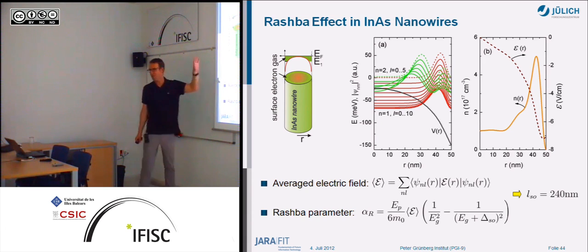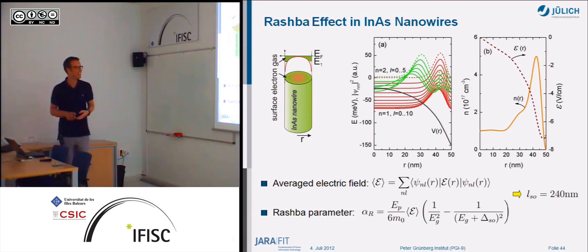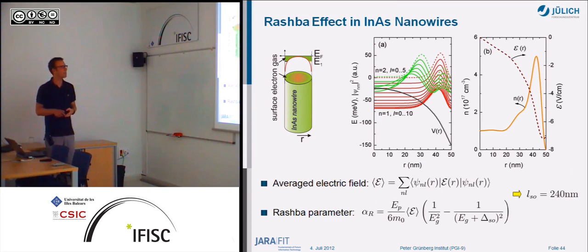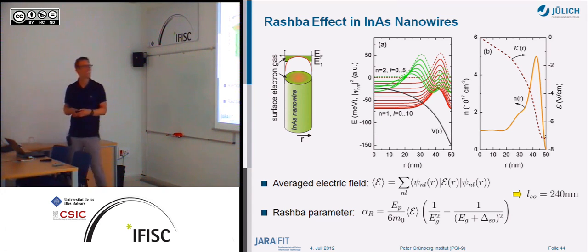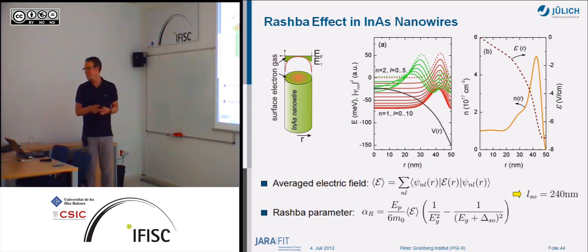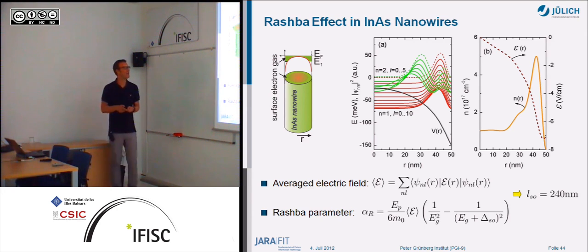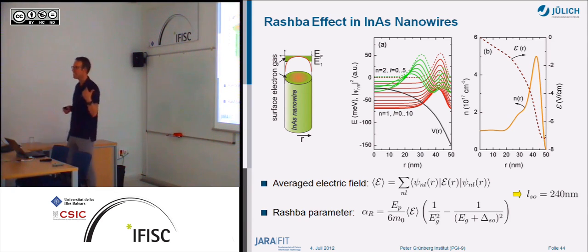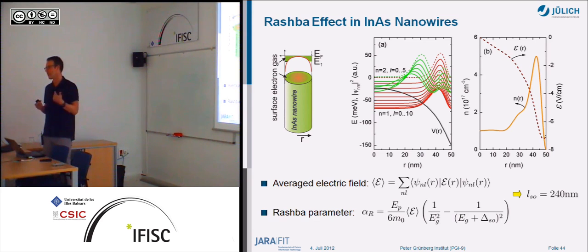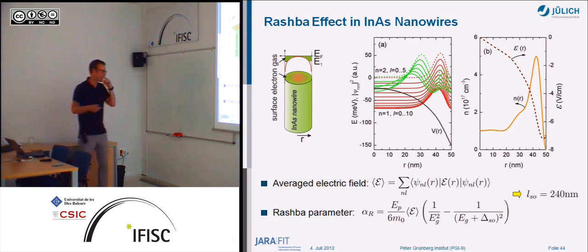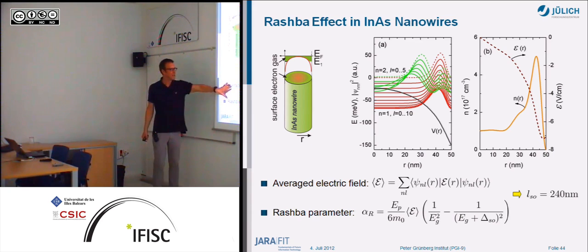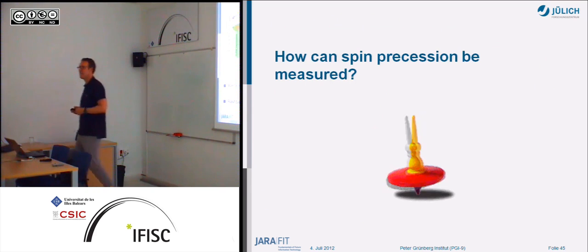To be honest, I don't feel that well about this assessment of the spin-orbit coupling lengths because, as some experts here know, you have to look at the interface as well, how the electron wave is penetrating into that barrier, into the vacuum state. For that system, you really have a hard time knowing what's going on. So you can do some assessment here, but I would say one can do better if one knew better how the interface looks in detail.